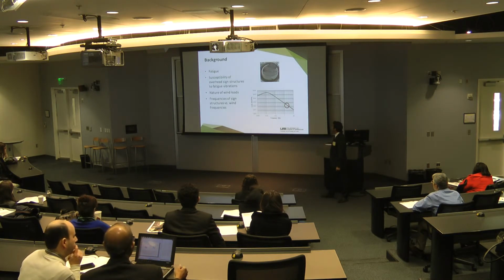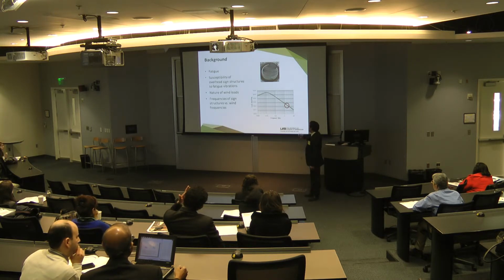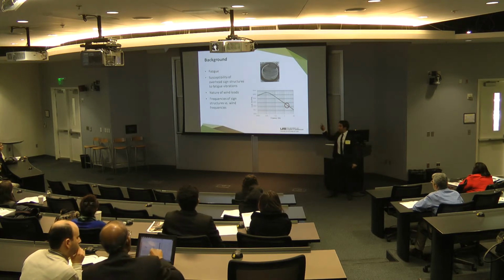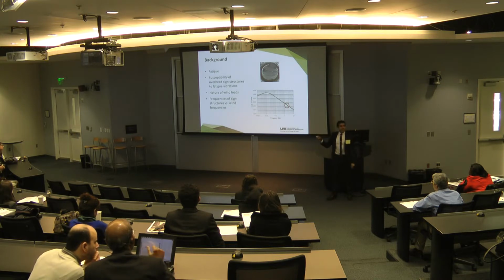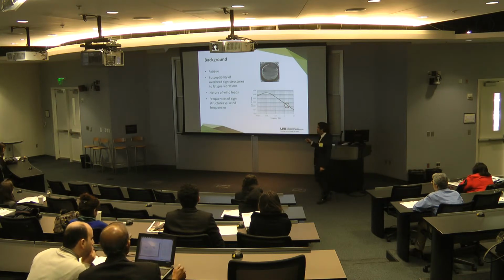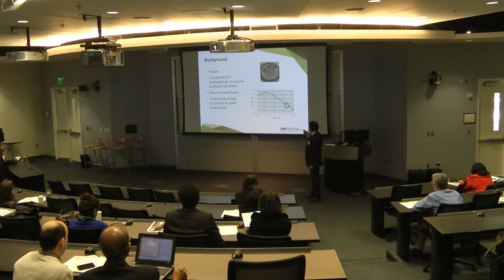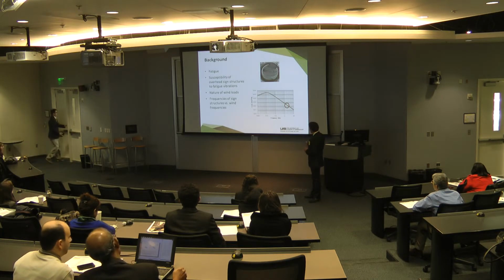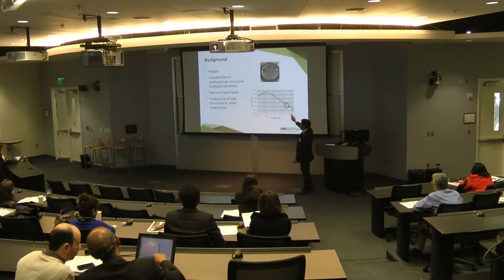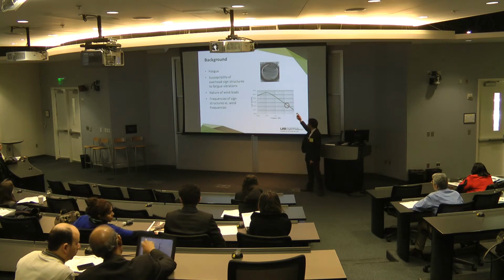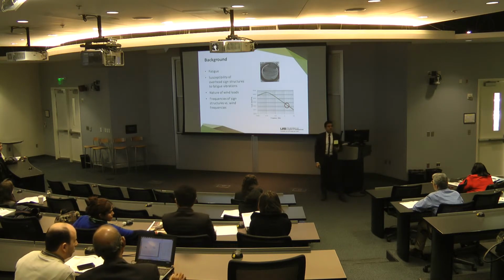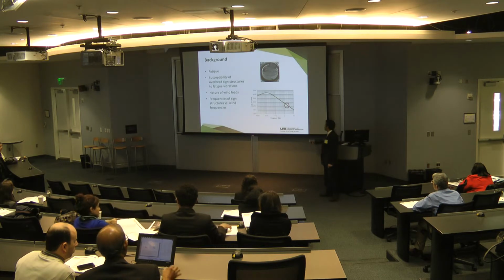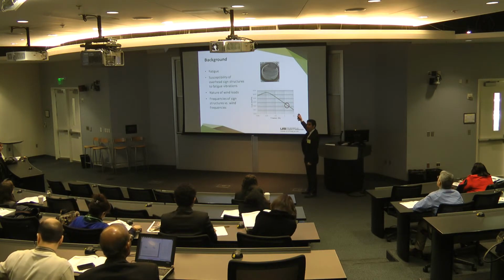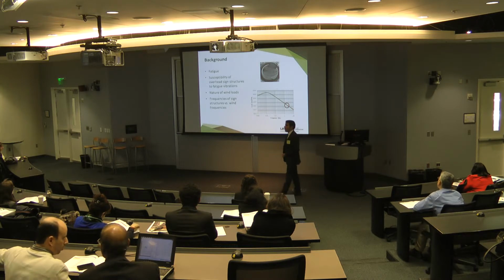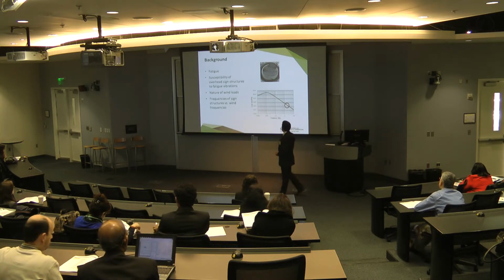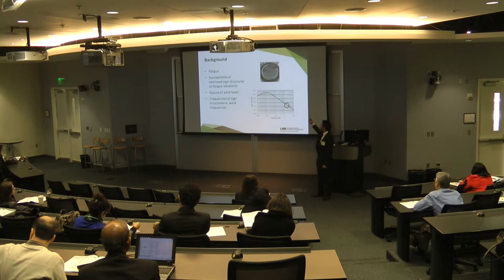I'd like to give a background for fatigue. This graph is for bolts failing in fatigue. Fatigue is a degradation of material strength due to cyclic loading. It starts with crack initiation at the lower side of the cross-section, as shown here. Then this crack starts to propagate. This propagation can be seen in the beach marks in the cross-section until the cross-section couldn't sustain the load anymore. Then it suddenly fails, as shown in the upper part of the cross-section.